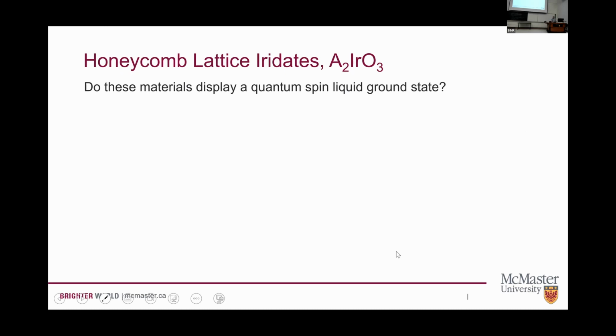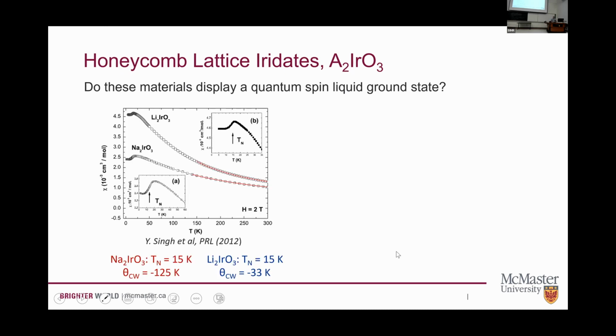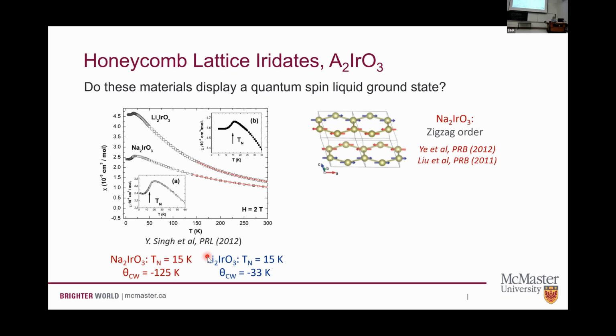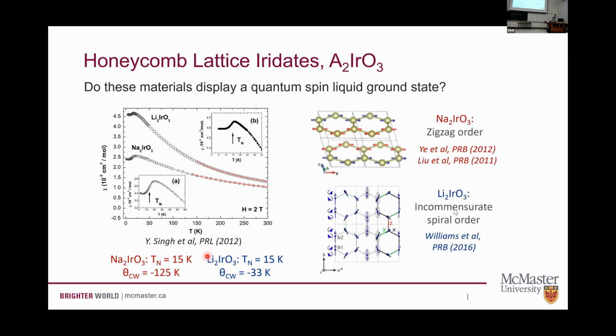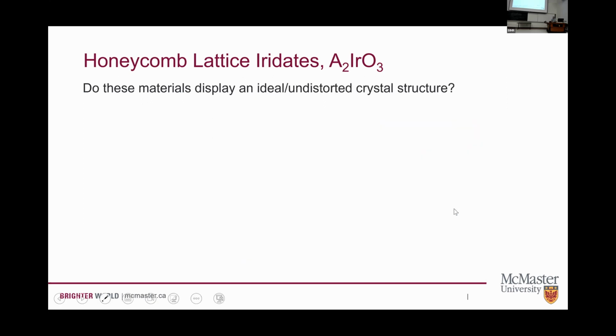And so when we do this, do we find quantum spin liquids? No. These materials develop magnetic order at relatively low temperatures, so at about 15 Kelvin. Both the sodium and the lithium honeycombs develop magnetic order. It's long range order. There's some sign that these are frustrated, so they order at lower temperatures than the magnetic interaction strength might suggest. In sodium, we get the zigzag magnetic order state. In the lithium case, we get a more complicated incommensurate spiral order. So if they're not quantum spin liquids, maybe they're close.